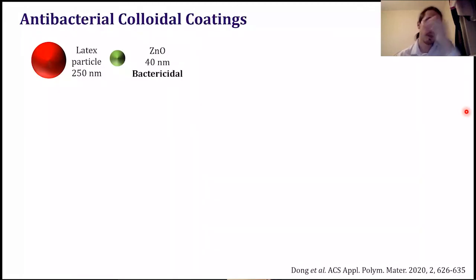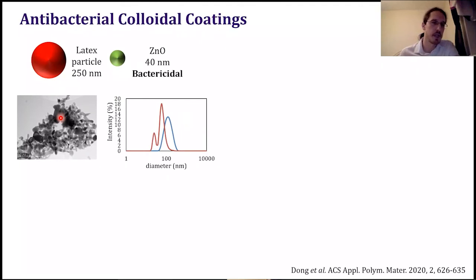So what Yi-Chen did was blend, again, large latex particles, which form a film, with zinc oxide nanoparticles, which are bactericidal. These particles, I paint them spherical, but zinc oxide nanoparticles have a shape which is definitely not spherical, as you can see there. And although the nominal size was 40 nanometers, we have two peaks here, and 40 nanometers is maybe in between those two peaks. But still, we followed a similar procedure, and blended the zinc oxide and latex particles with different concentrations of zinc oxide.